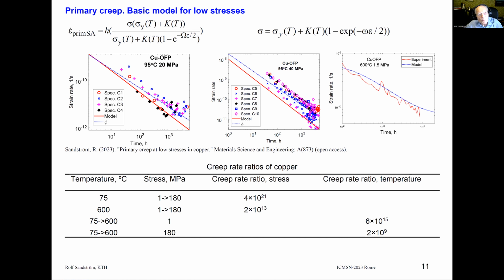Now I move to primary creep as the first phase of creep. Here is one model. There are several models, but here's one model of how you can describe primary creep. So instead of the stress here, you replace it by this expression. And these parameters here are related to those involved in the stress strain curve. And then you can see both from the experimental and the modeling results that you get a straight curve in a strain rate versus time in this double logarithmic diagram.